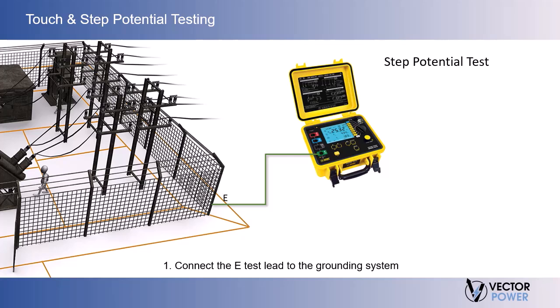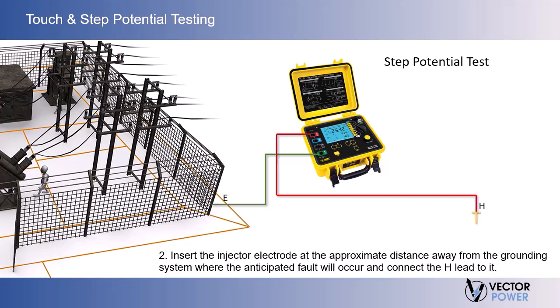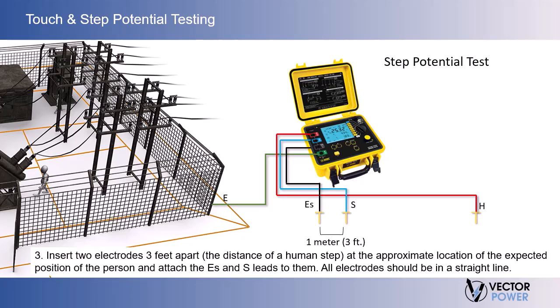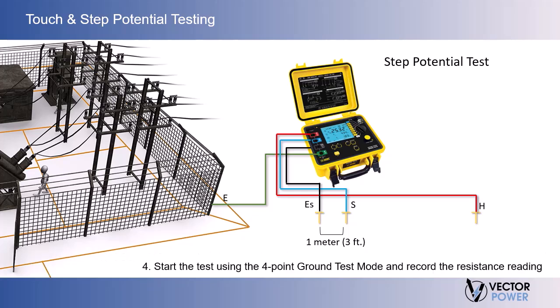To perform the step potential test, first connect the E test lead to the grounding system. Next, insert the injector electrode at the appropriate distance away from the grounding system where the anticipated fault will occur and connect the H lead to it. Third, insert 2 electrodes 3 feet apart, the distance of a human step, at the approximate location of the expected position of the person and attach the E sub S and S leads to them. All electrodes should be in a straight line. Start the test using the 4-point ground test mode and record the resistance reading.